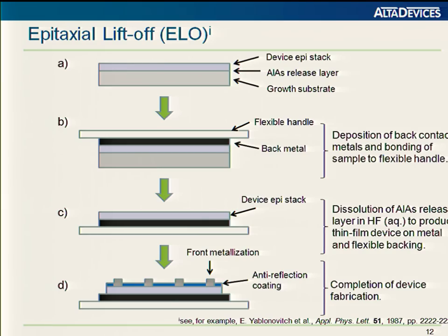How would you show something like that in an experiment? We fabricate our devices both in our baseline process as well as our research process by MOCVD growth of an epitaxial stack with an aluminum arsenide release layer. It's grown sunny side down, so what later becomes the front of the device is grown first. That gives us access to the back side of the device to engineer the optical properties of that reflector. It's bonded to a plastic substrate, so the final device is flexible. This is then submerged in hot hydrofluoric acid, which dissolves the aluminum arsenide layer. And if we invert the structure, we end up with this thin film on the reflector on plastic, and the wafer is left largely undamaged, available to be reused.